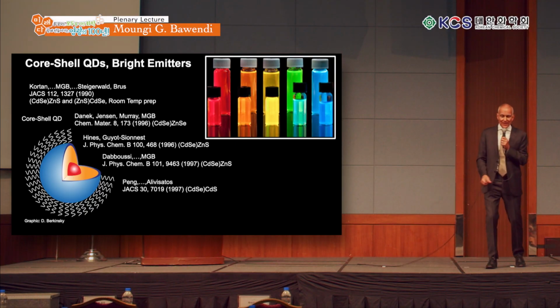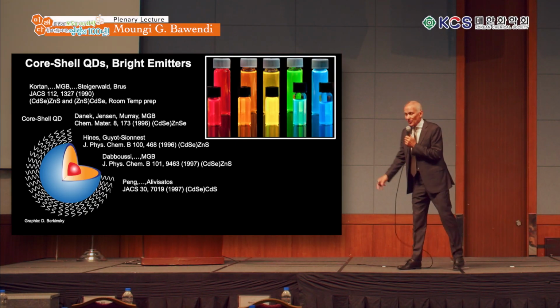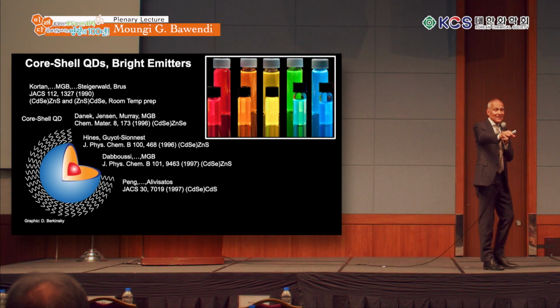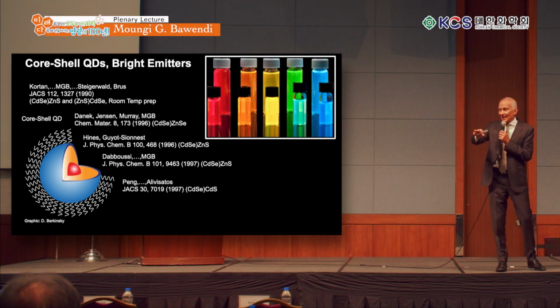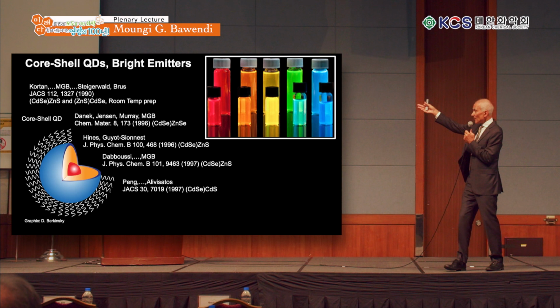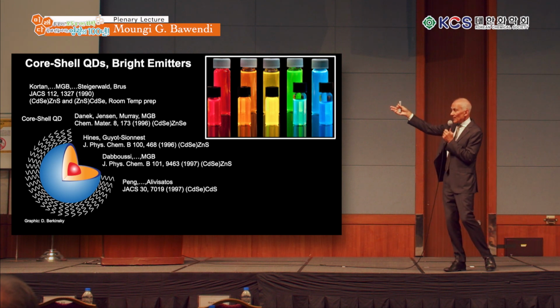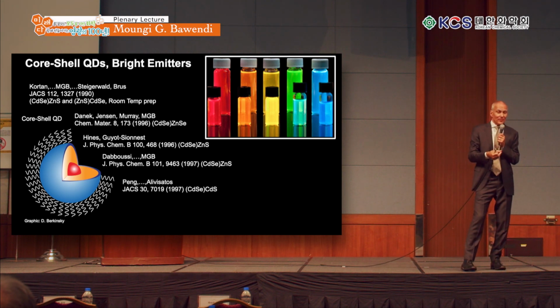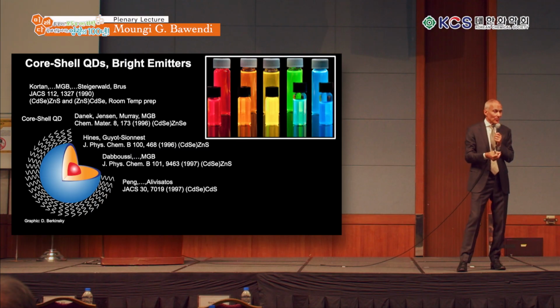A big advance came in the 1990s, so remember, the discovery was in 1980, early 1980, 81, 82, 83. It took 10 years from that discovery for the synthesis to appear. Once we had good samples, then things went much faster. We were able to do physics on it, and this discovery of making core shell materials to really protect the quantum dot from the environment allowed the quantum yield to go up to 100%. And then we were able to begin to apply it.